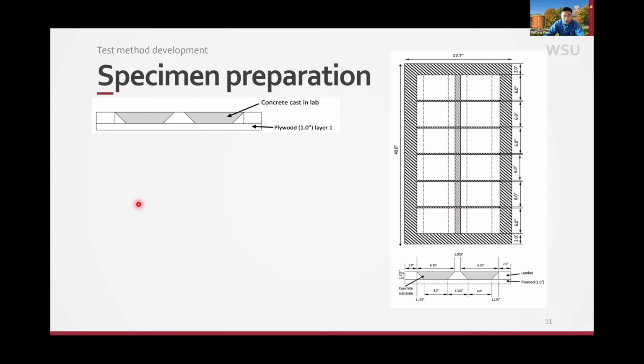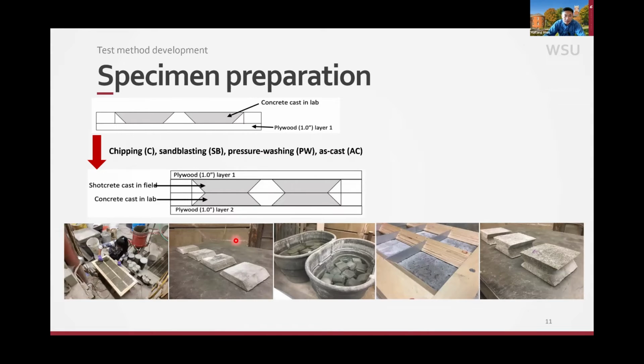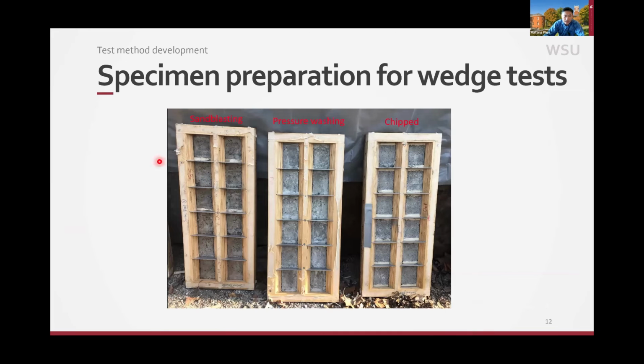For the sample preparation, especially for the wedge test, you cast the concrete in this panel for making the different samples, and we cast our concrete in plywood. Then we do the surface preparation of the concrete. You either do chipping, sandblasting, pressure washing, or you don't do anything to the existing concrete. We call that as-cast. Then you flip it over, and then you place the shotcrete. So here's an example of the concrete before application of the shotcrete.